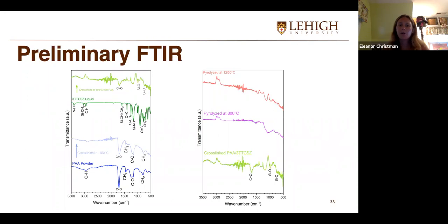And then I also have plotted some preliminary FTIR, which I'm still working on because, as you can see, there's some noise in some of these samples. So I might be taking some other scans or looking at other data that I have. But it's good to see that our 3TTCSZ liquid sample has a very clear signal and all of these peaks match up with the molecular formula. So that's definitely good to see. The pyrolyzed samples are not super helpful because they don't have any hydrogen in them, so there's not really any clear peaks here. I'm just going to be continuing to work on these.